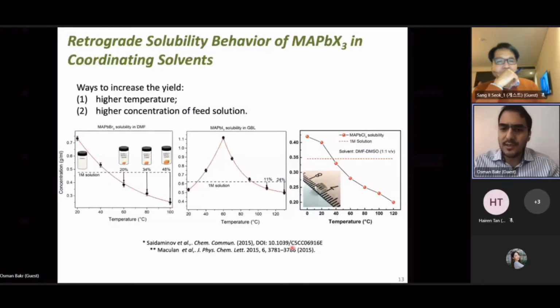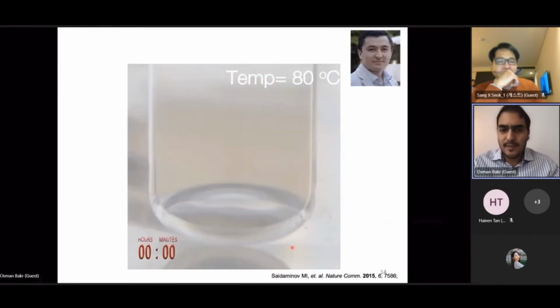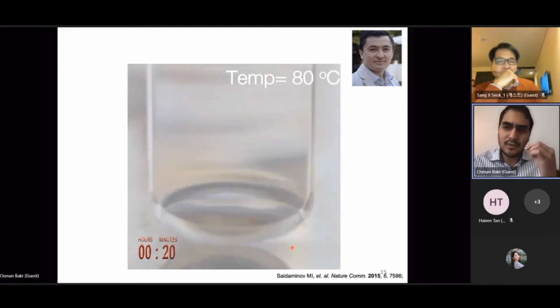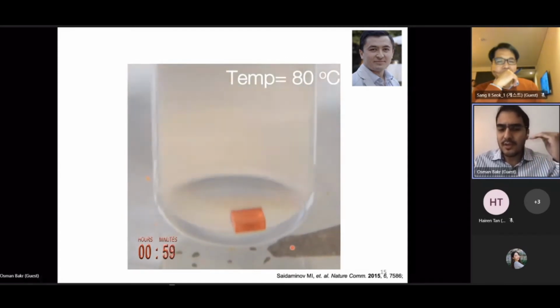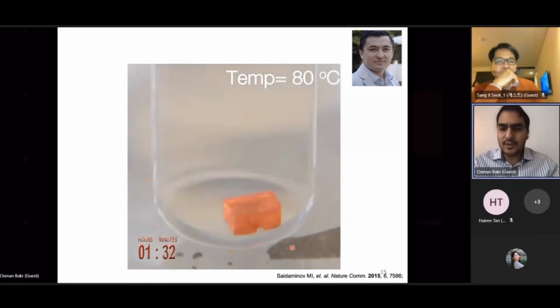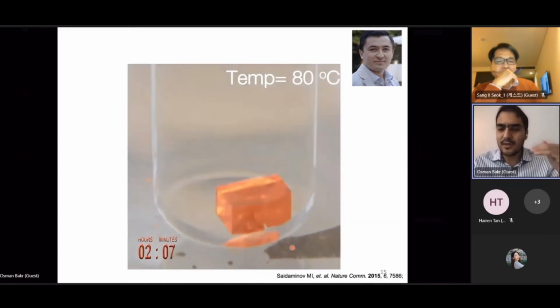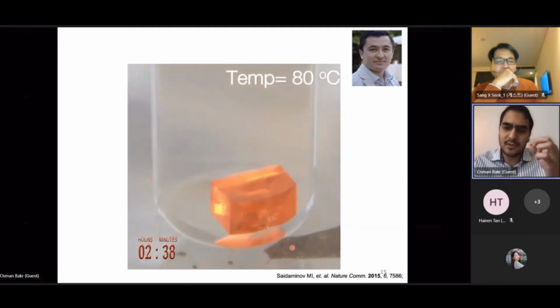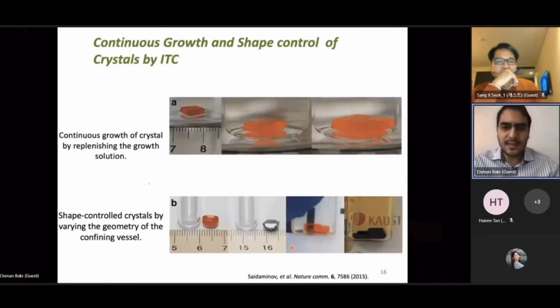And we measured the solubility of different perovskites in different coordinating solvents, and we found that indeed the solubility drops as you raise the temperature. Sometimes it's non-monotonic. And just to give you an idea, when you raise the temperature, you're suddenly putting the solution under conditions of supersaturation. And if you do this carefully and you nucleate with just one crystal, you can, in a matter of minutes and hours, grow a crystal that normally takes a week to grow. Okay? So this was an exciting discovery for us.